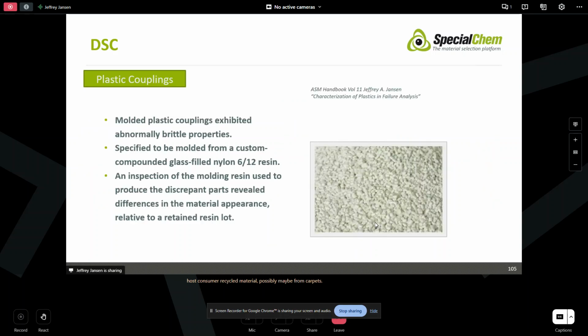Our next example is some molded plastic couplings that exhibited abnormally brittle behavior, specified to be a custom compounded glass filled nylon 612. Inspection of the molding resin used to produce those parts showed that those bad parts had some differences in the appearance of the individual pellets. So we grabbed some individual pellets.